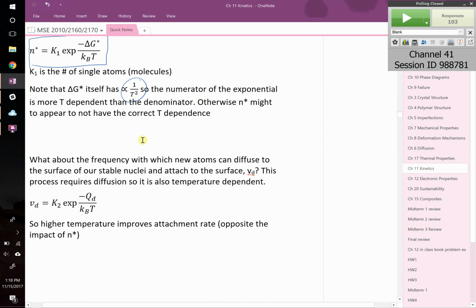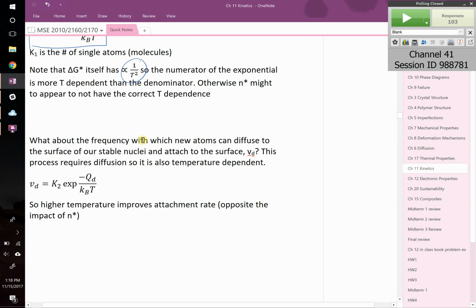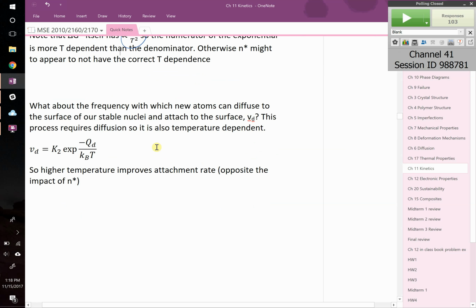All right. So that's how we nucleate things. That gives us a way to calculate how many critical nuclei should exist as a function of temperature, if you knew what K1 was, that constant. Now we need to figure out the rate at which these things will grow, or the rate at which new atoms will come and attach themselves to it. So we call that V sub D, right? That's the frequency with which new atoms come and attach themselves to the surface. That one is our typical thermally activated process.